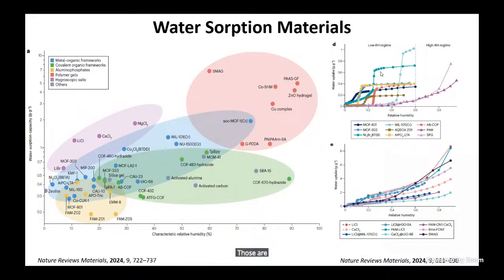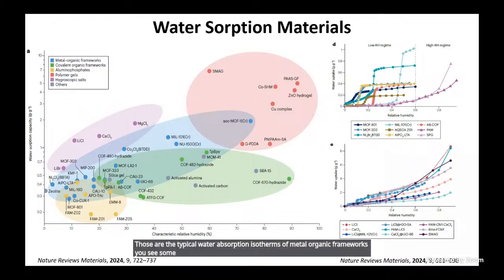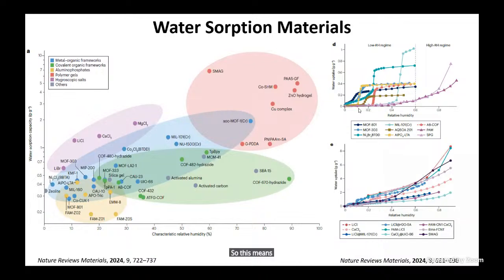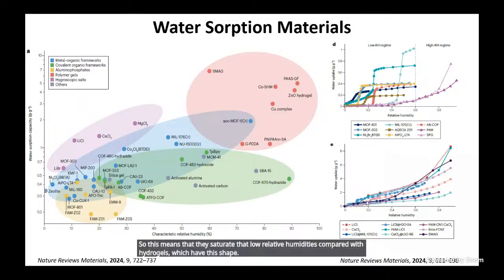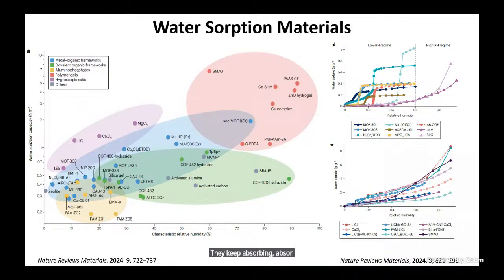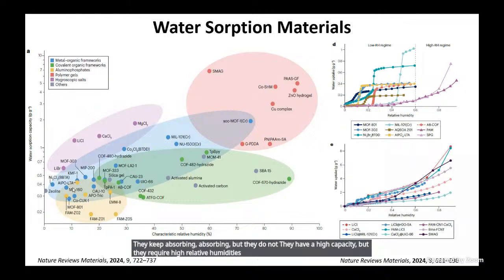Those are the typical water absorption isotherms of metal organic frameworks. You see some begin absorbing, but at a certain relative humidity, they have a sharp increase to saturation. So this means that they saturate at low relative humidities compared with the hydrogels, which have this shape. They keep absorbing, and they have a high capacity, but they require high relative humidities. So my idea was to combine both, right? Combine metal organic frameworks and hydrogels or polymers to see if there is some transfer of the water absorbed in here to these kinds of materials.